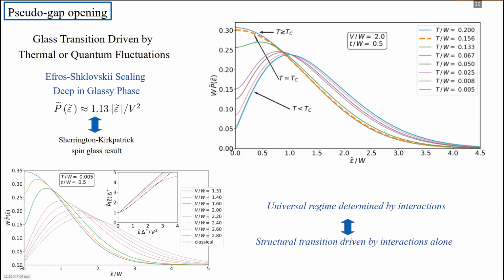So this scaling is shown on this figure here. The main figure just depicts the field distribution for different interaction strengths, and then the scaling collapse is shown in the inset. So after proper rescaling, all data collapse to a single curve. So we get this Efros-Shklovskii scaling, and one important point is that the slope of the universal scaling function is 1 over V squared. So it only depends on the strength of the interactions, showing that this phase transition is really driven by the interactions themselves. It is structural in this sense.